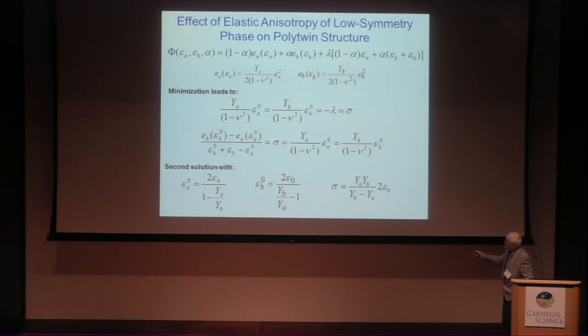That is the solution of this problem. That is where I show you stress. The area of stress, where we can expect, absolutely not predictable before, some new area of existence of a polydomain state. This stress, if the elastic modulus is different by 50%, we can expect something like epsilon 0 multiplied by 0.5 multiplied by the modulus. So it's not such a huge stress.